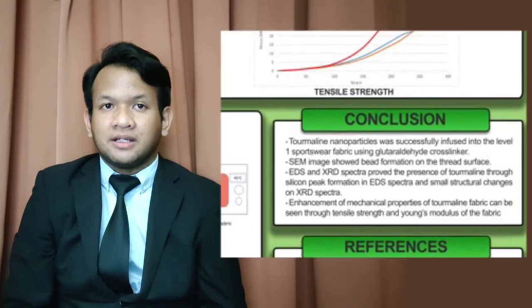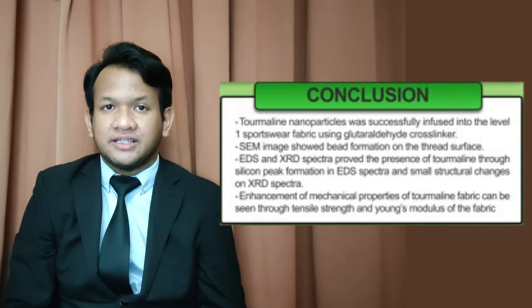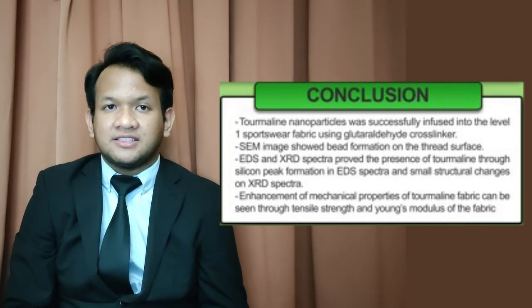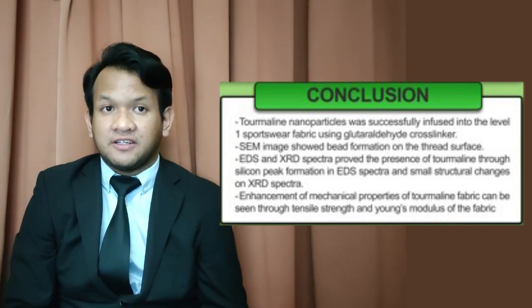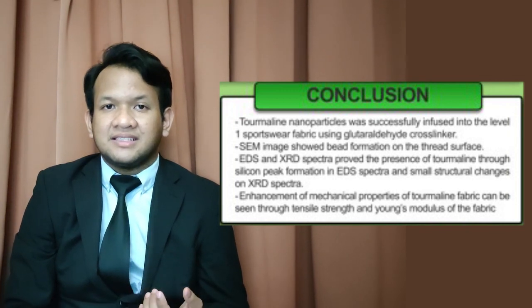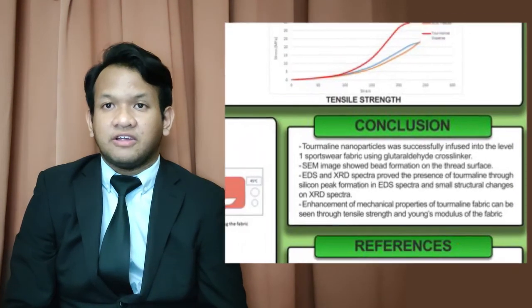As for the conclusion, tourmaline nanoparticles were successfully infused into the level 1 sportswear fabric using glutaraldehyde crosslinker. The SEM image showed bead formation on the thread surface of the tourmaline-infused fabric. Next, EDS and XRD spectra proved the presence of tourmaline through the formation of a silicon peak in the EDS spectra and small structural change in the XRD spectra. Lastly, the enhancement of mechanical properties of the tourmaline fabric can be seen through the highest tensile strength and Young modulus of the fiber.